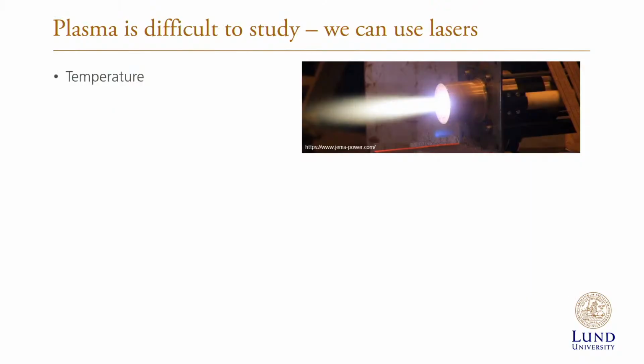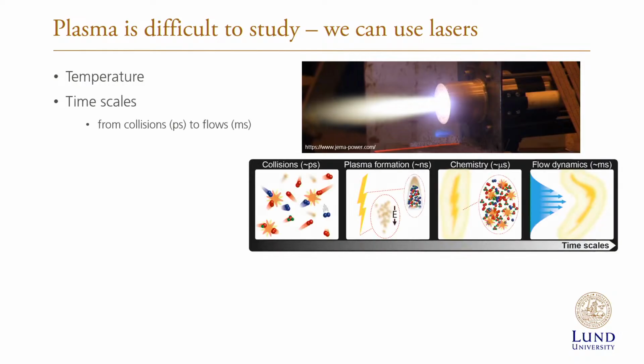Well, we study it with lasers usually. And from that, you can get temperatures, because you can't put a thermocouple or something like that into your plasma. It'll burn. There will be nothing left. So you have to look at the light. Right? So you send light in, you take light out, and then you can measure the temperature. You can measure different time scales,